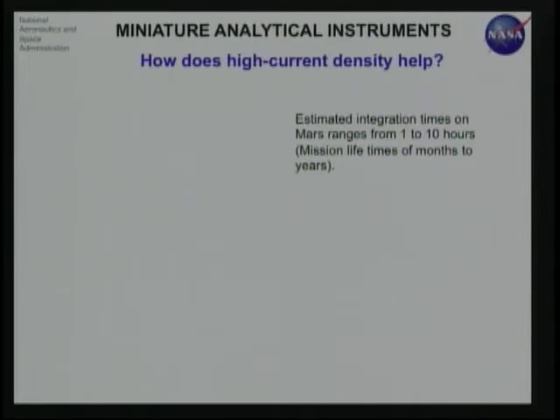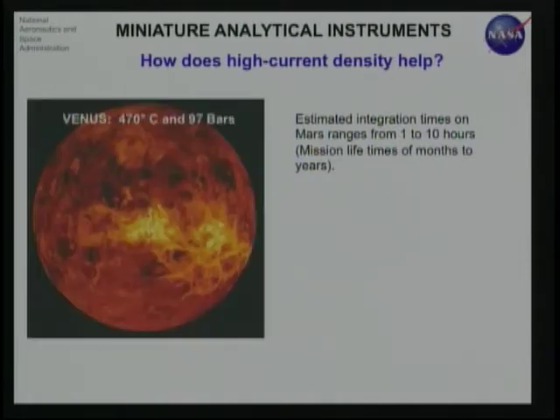How does the high current density help? Carbon nanotubes, with the architecture of nanotubes we have developed, give you very high current densities. The high current density helps because you can make up for lower acceleration voltage by producing a lot of electrons, which will produce higher flux of X-rays.